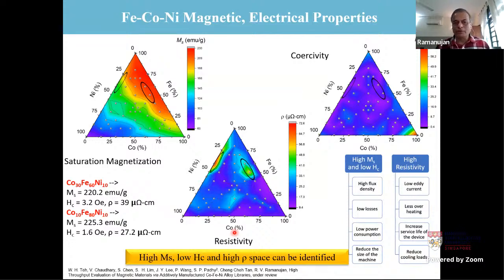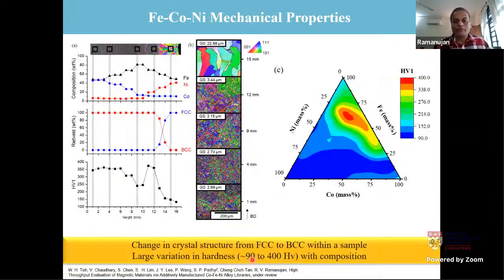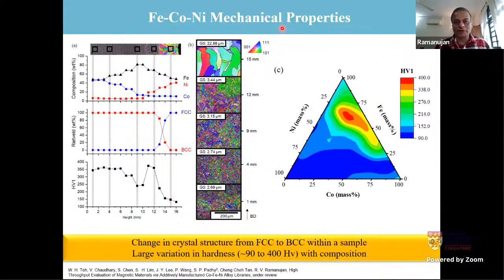So by these methods, we could identify new compositions which have good combinations of, for example, magnetic properties and electrical resistivity. So for example, cobalt 30, iron 60, nickel 10, or cobalt 10, iron 80, nickel 10 can give you high MS, low HC, and high resistivity. So we could find out these are the interesting compositions. We could also do mechanical properties using nano indentation, and again produce a map of the mechanical properties as a function of composition. So you can find out, for example, that this area in red has the highest hardness. So that's promising from the strength perspective.